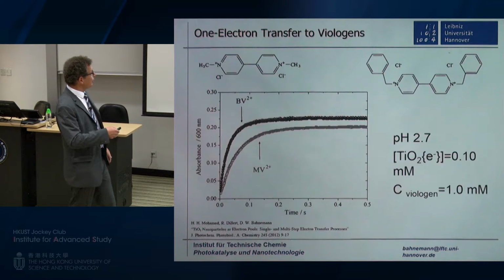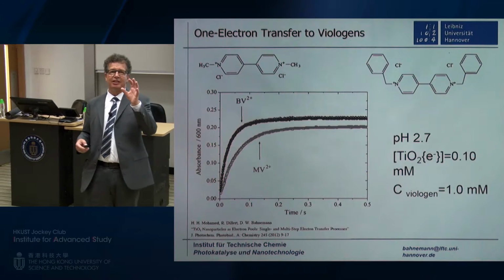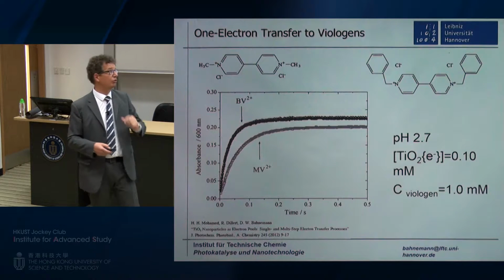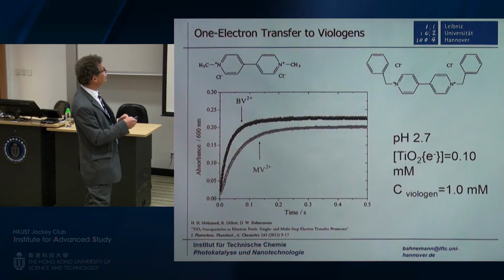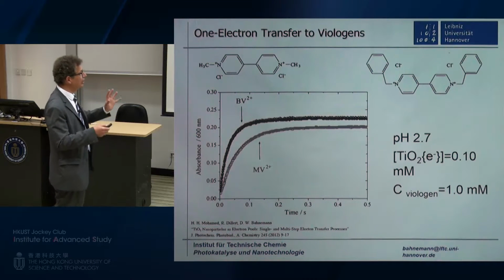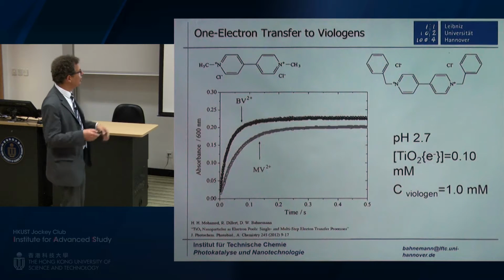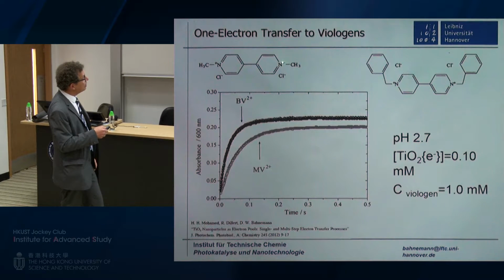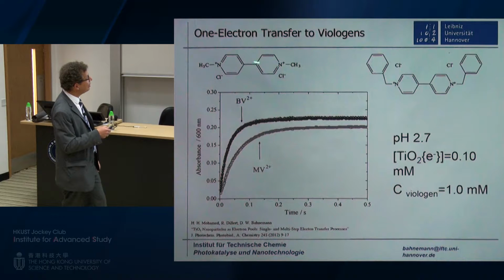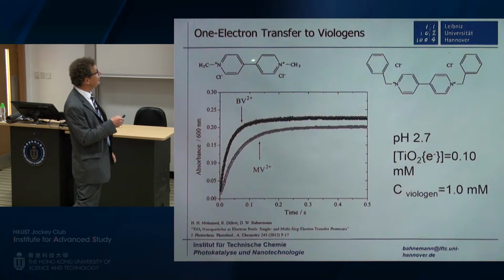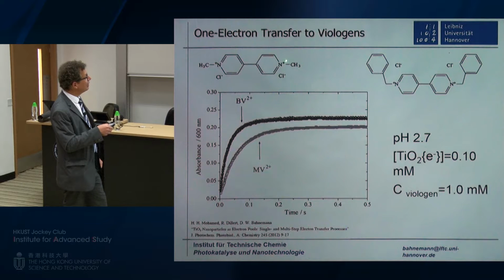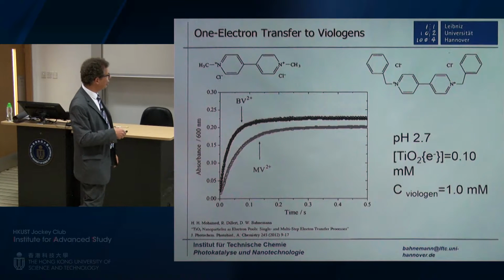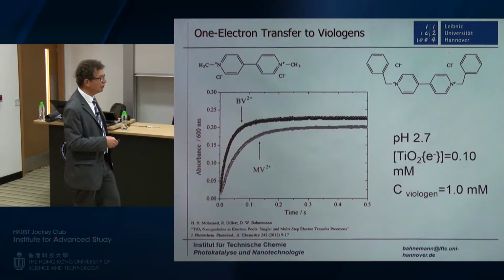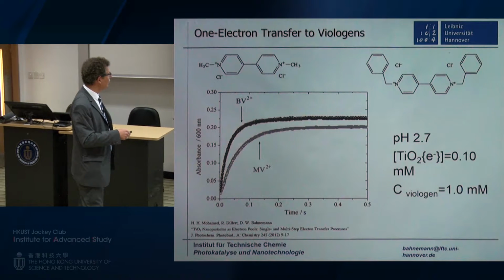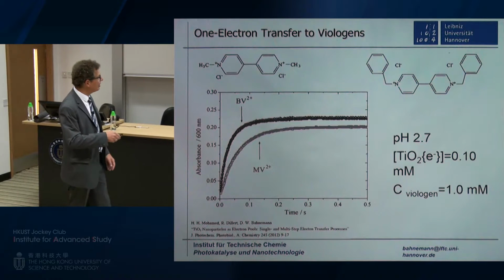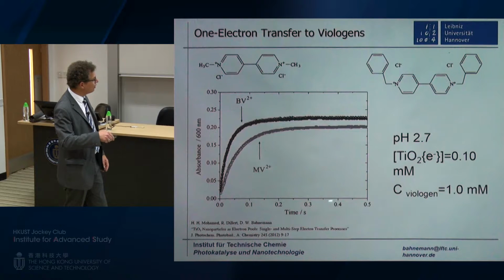And now you can go on like this. Before starting with an easy electron acceptor, I take something which is a well-known electron acceptor and a well-known mediator for electrons. This is this molecule, methylviologen. It's so well known that research started with this molecule some 30, 40 years ago, because these positive charges like to accept electrons, and before it's a dication, and once it accepts an electron, you get a radical cation formed, and this radical cation has a very strong color with a very high extinction coefficient of several 10,000. And so what you see is actually not that the blue color fades away, but you get additional blue color formation over time when you mix your electrons.